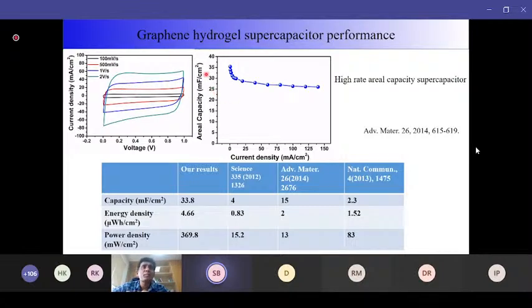And we checked its areal capacitance. The areal capacitance is more than around 33.8 millifarad per centimeter square, and with the increase of current density, which means we are charging and discharging at a faster and faster rate, at the highest current density, around 130 milliampere per centimeter square, it leads to the charging of this device within some hundreds of milliseconds. And this result we have compared with papers published at that time in highly reputed journals. We compared with them and this capacitance is really high. The energy and power are much higher as compared to those publications.